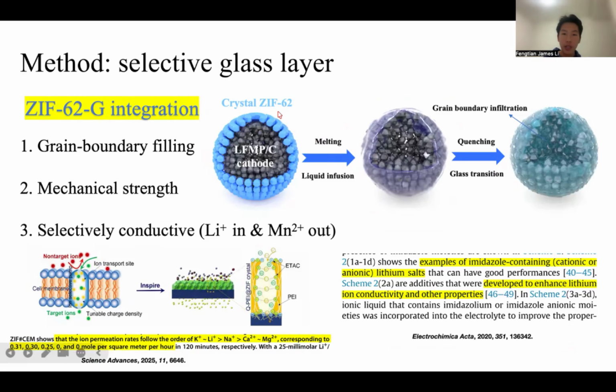So as you can see, we are integrating the crystal ZIF-62 onto a LFMP-C cathode. And this cathode, just for some context, is a frequently synthesized cathode in previous literature, so it's already mature. But we are adding another protective layer to enhance its conductivity and structural stability. After we melt this crystal, it transitions into glass. And because it has a liquid phase in the middle, it can infiltrate into the grain boundaries to form a conductive and continuous layer.